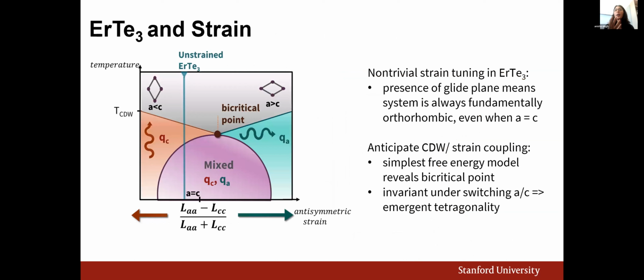Now, when we talk about strain tuning in the rare earth telluride crystal family, it's a bit non-trivial what the effect of uniaxial strain will be. And this comes back to that glide plane that I mentioned a few slides ago. Because of this glide plane, that's a symmetry operation that does not couple to strain. No amount of strain can ever undo that glide plane. So even at the point where we strain tune the system through the point where the in-plane lattice parameters are equivalent, the system is still fundamentally orthorhombic. The system still knows those two in-plane directions are different.